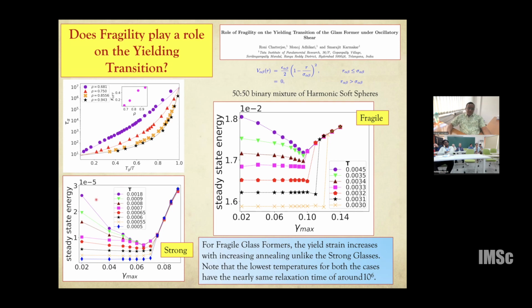And for the strong case, what we found is that the phase diagram, or the annealing property, changes significantly. One interesting point is that if you start from poorly annealed, then your annealing goes on and on and on. At some point it stops, and beyond this oscillatory amplitude you start to yield, and there is no longer any annealing. But the point at which you yield remains very similar, even if you increase your annealing. If you go to lower and lower energy states, or better annealed glasses, your yield point does not shift.